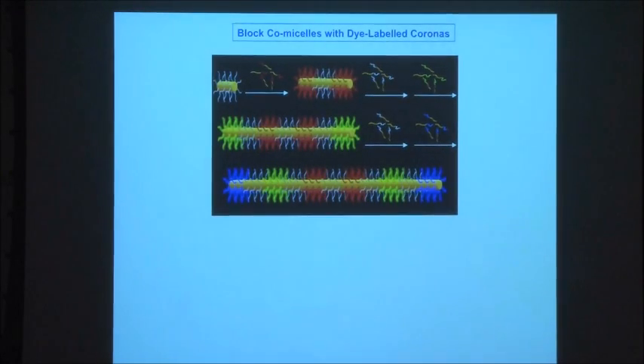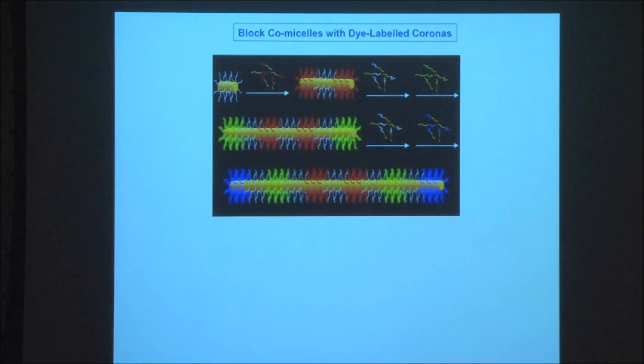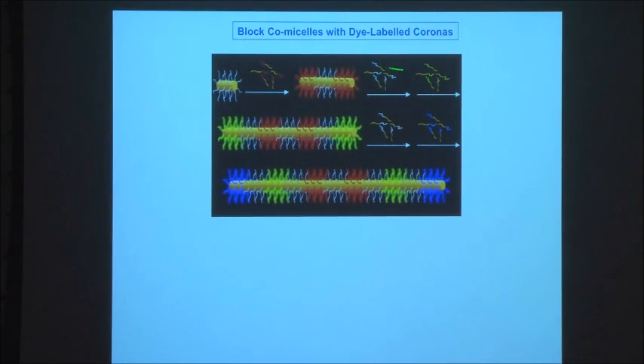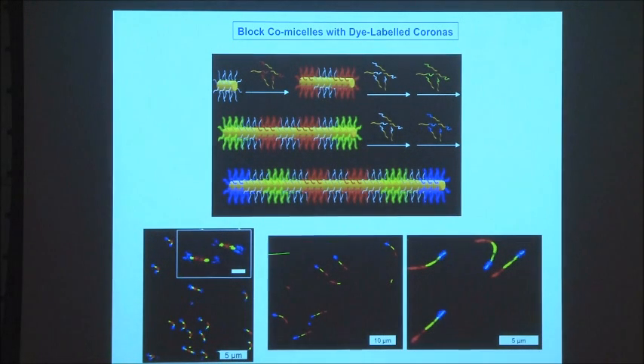Some other things we've been looking at in terms of functionalizing the corona is making encoded structures and nanopixels. Using these fluorescent dye functionalized block copolymers that I described earlier, instead of using them all at the same time to make random structures, you can make block or segmented structures. So you can start with a micelle with no dyes in the corona. You can add the one with red dyes, which adds on each end. Then you add a bit of block copolymer with no dyes attached, and then you add the green one, and then another spacer layer with no dyes, and then the blue one, and you can build up these types of structures.